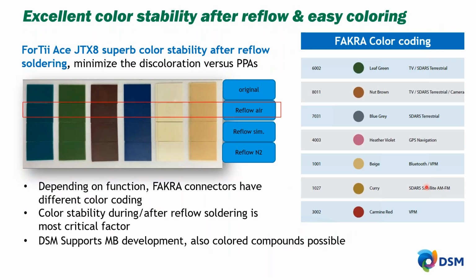We mentioned color as a requirement for the reflow process. So the color fastness is important. And ForTii Ace JTX8 has great colorability and great color fastness as it goes through the heating process. You can see even in a variety of different color palettes here, as these plaques were subjected to heat similar to the reflow process, very little or no change in color, even in the different color families. This is especially important in the newer automotive FAKRA connectors. These FAKRA connectors have a color coding scheme that dictates for the final assembly operation what lead gets plugged into which connector. So it's important that the color fastness be appropriate so that someone can, for example, distinguish beige from curry color. And these colors are set in the FAKRA color coding standard.